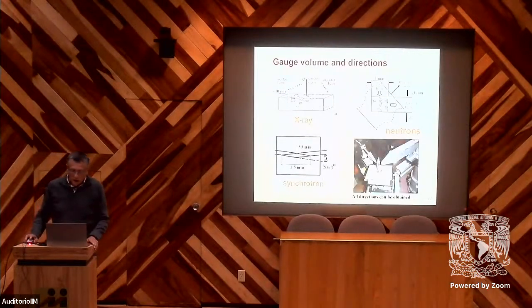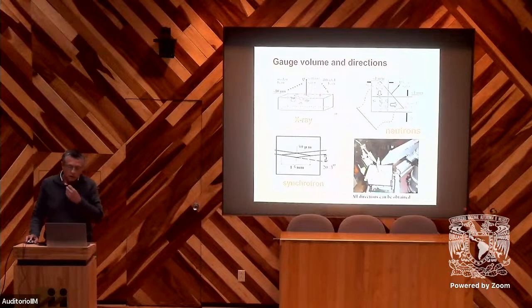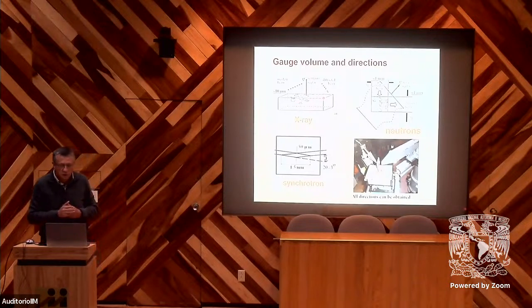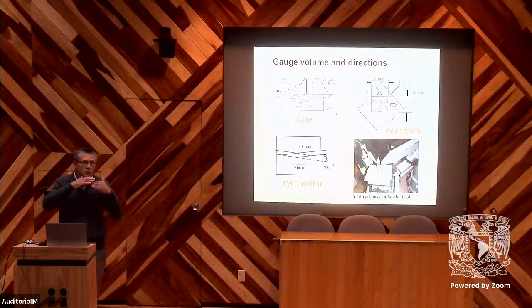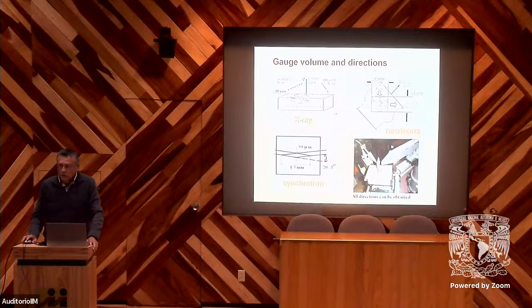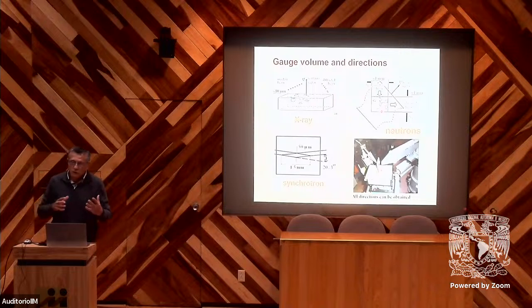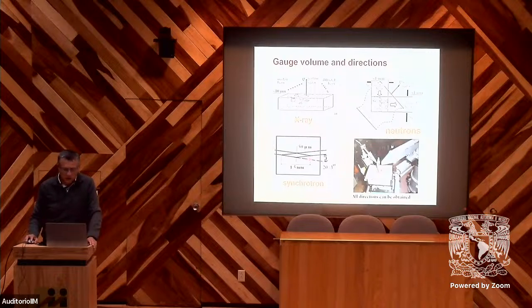So we can use classical X-ray. And we know that X-rays are strongly absorbed by metallic materials. So that means the measurement will be near the surface, typically 10 microns. And if we want to measure inside the material, we use neutron diffraction. The advantage of neutron diffraction is that we can measure in all directions. And we have an intermediate penetration with synchrotron radiation.